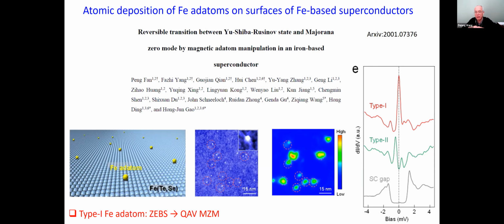But the most convincing explanation, I think, is the surface inhomogeneity due to the alloying. Some parts may have topological surface states. Other parts may have a void or a different kind of surface state with different chemical potential. So you can think the type 1 iron atom sits in a region where there are well-defined topological surface states with low chemical potential. When the chemical potential is too high, the topological property is gone. And the type 2 adatom sits in the region where the surface states are very nicely protected, just like what's been observed by ARPES.